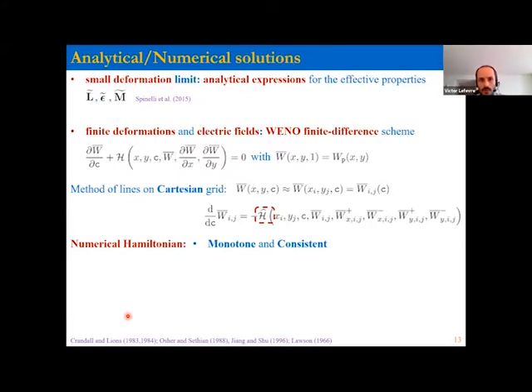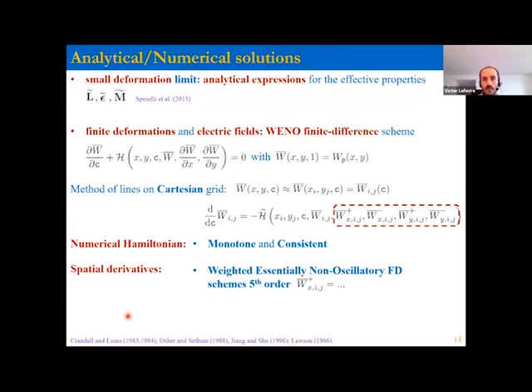So the rule is, for instance, that the numerical Hamiltonian, that's what you put in the computer, needs to be monotone and consistent. There are a number of these in the literature, so we used one of them. Then you need to evaluate the spatial partial derivatives with respect to the space variables. To do that, we used the so-called WENO, weighted essentially non-oscillatory, finite difference scheme. It's a fancy finite difference scheme because it's fifth order accurate when the solution is smooth and remains third order accurate when you have discontinuities in the solution or in its gradient. And that's something that we may expect. That's typical for solutions of these PDEs.